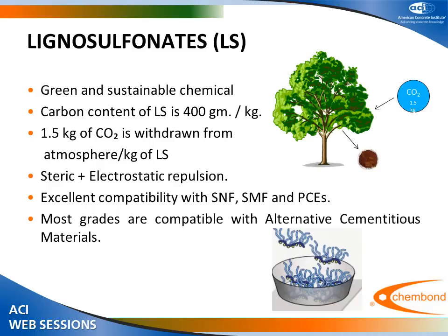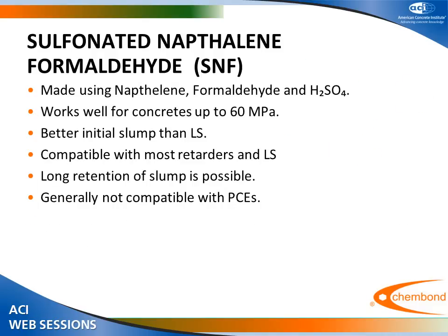And what they say is carbon content of lignosulfonate is 400 grams per kilogram. Actually, this 400 gram per kilogram comes from 1.5 kilo carbon dioxide, which is absorbed from the atmosphere. It has steric and electrostatic repulsion, and basically the diagram below mostly gives indication of the polycarboxylates, but I'm indicating that also lignosulfonate has steric repulsion ability. Naphthalene sulfonate, everybody knows, made from naphthalene and sulfuric acid, and is good for concretes up to 60 megapascals. Generally compatible with lignosulfonates, but not with the polycarboxylate ethers.